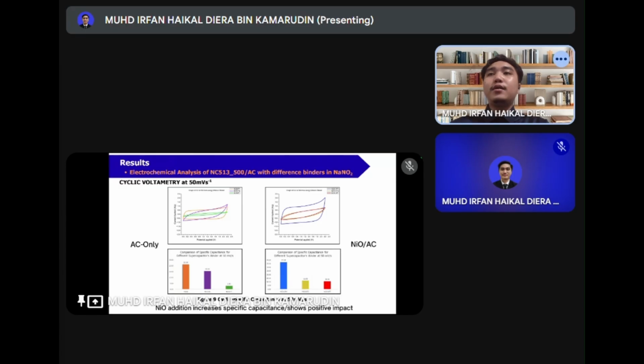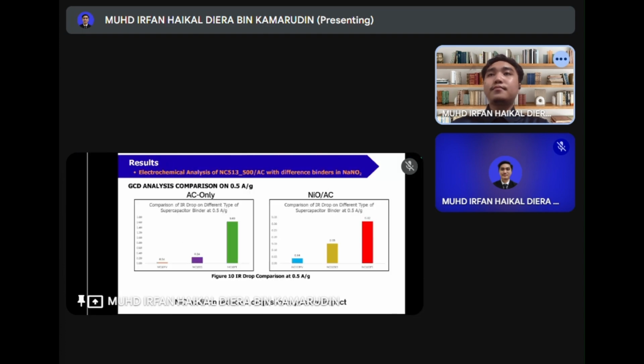The key findings are PVDF gives the highest specific capacitance in both systems, consistent with its strong performance as a commercial binder. Meanwhile, Tapioca Starch performs well with the AC-only electrodes but shows a slight drop with NiO. Still, it maintains good stability and conductivity, making it a promising eco-friendly, low-cost alternative. And lastly, PTFE has the lowest performance in both cases, likely due to weak contact and poor ion transport.